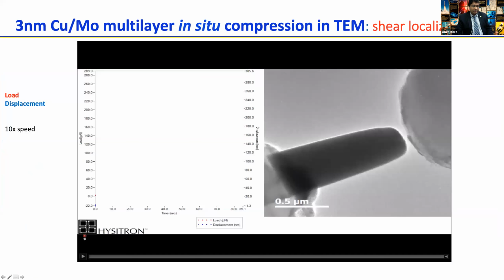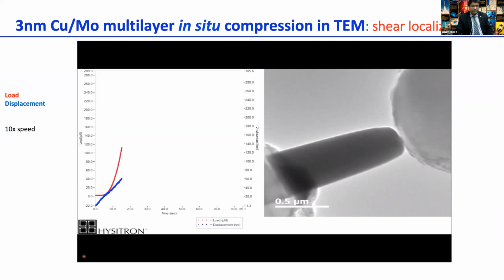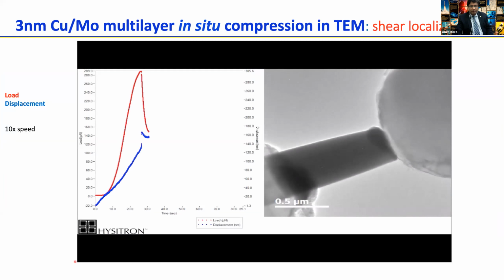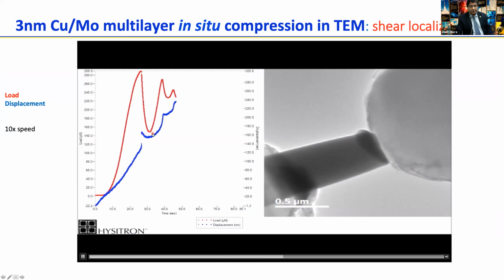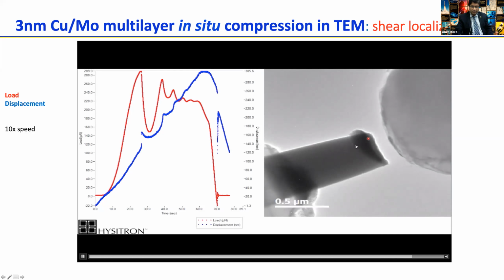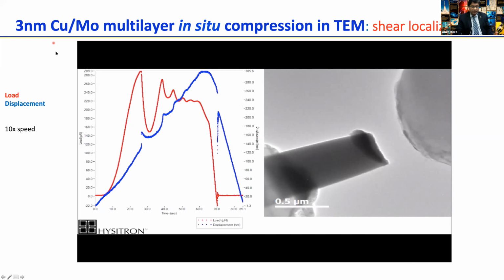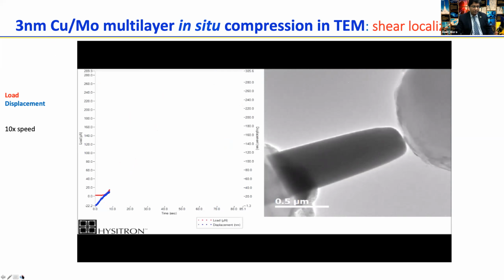So all that is good, but what's the limitation? As this material becomes so strong, at the point of yield, so this is a 3 nanometer multilayer, this was deformed inside a transmission electron microscope in situ. And you saw that a shear band nucleated at the point of yield, creating a huge load drop, which means at the point of yield, when the layer thickness is only a few nanometers, we have dislocations sliding across the interface. So once plastic deformation starts, it localizes in the place where it starts. And that shear localization limits the ductility and the toughness.